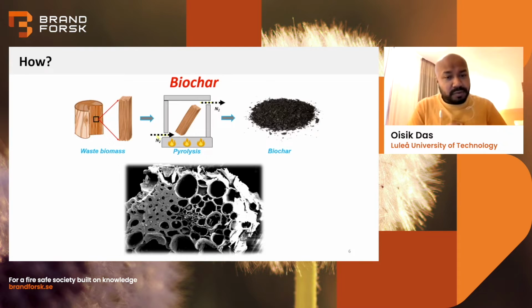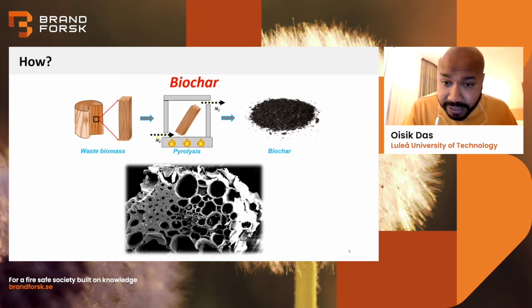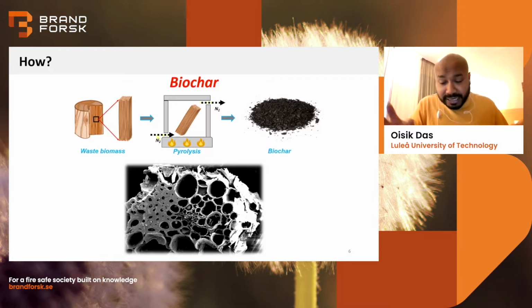So how do we make biochar? We take any kind of waste biomass. It can be waste wood, branches, leaves, any kind of waste biomass. And we heat that biomass at high temperatures, over 500 degrees centigrade, below 1000. It can be lower than 500 or more than 1000, but usually the range is from 500 to 1000 degrees centigrade, in absence of oxygen or with a low amount of oxygen. And then we get a black solid material, which looks like charcoal, but our reaction is more controlled. We get a solid powder, which looks like the photo you see, a macroscopic photo with a lot of pores, and it has a carbon skeleton.